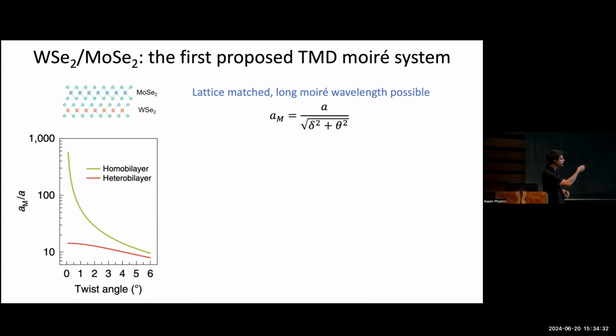So first of all, these two compounds, even though they're different chemical compounds, actually their lattices are very close to match. And the Moiré wavelength is dictated both by lattice mismatch delta and also the twist angle theta. So for most heterobilayers where there's a lattice mismatch, as you decrease the twist angle, eventually this delta squared term in the denominator dominates, and your Moiré wavelength has some cutoff. You can't go past a particular wavelength. On the other hand, for lattice matched compounds, you're mostly dictated by theta, and so your Moiré wavelength can diverge and take you to a strongly interacting regime.